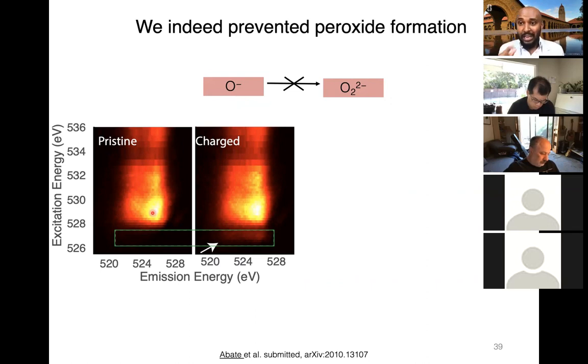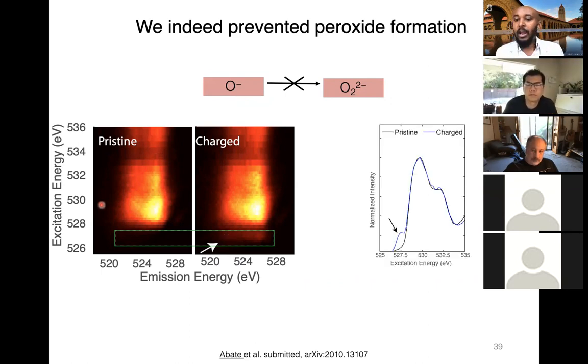But the most important change again happens after charging, after ionic redox, where in addition to the bright feature we commonly observe, we also have this faint feature that appears close to 527 eV. If you plot this information a different way by integrating this bright feature onto the y-axis, this is similar information plotted differently, where I'm showing the pristine material in the black line and the charged material in the blue line. As you can see, the most important change happens around 527 eV, with the formation of this new peak upon charging.